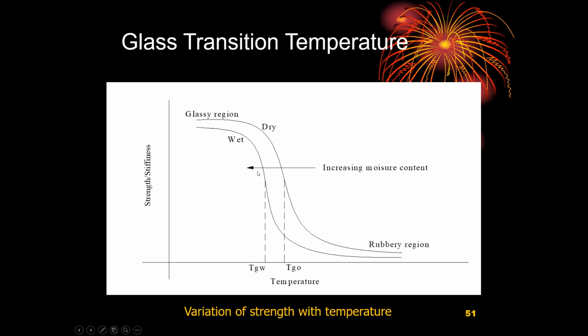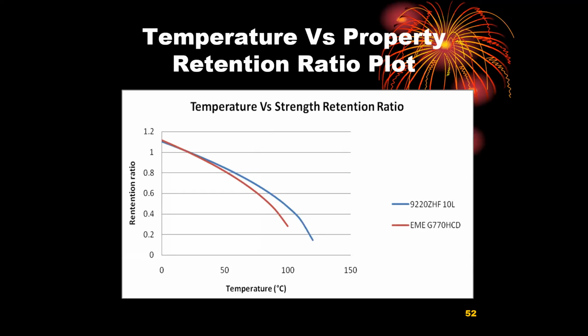And when you consider the maximum operating temperature, where the moisture susceptibility or take-up of moisture is more, we are in for slight surprises here and there, as the maximum operating temperature must be at least lower by a comfortable factor compared to the wet TG of the encapsulant material. Coming to the retention ratio that was plotted from some of the quite proven analytical equations, for the various encapsulant compounds we find that anywhere from 110 to 130 degrees Celsius were the end. And it was not able to give us a failure analysis based safety factor beyond that.